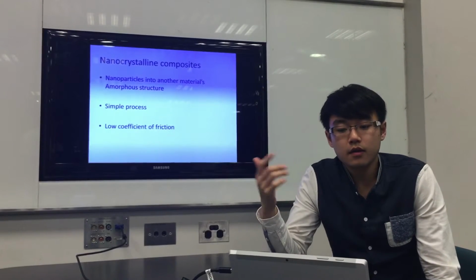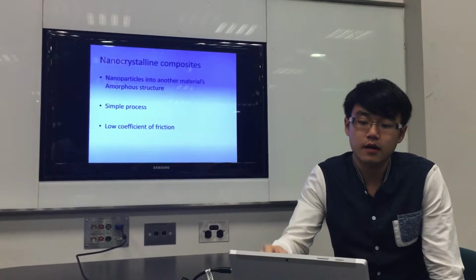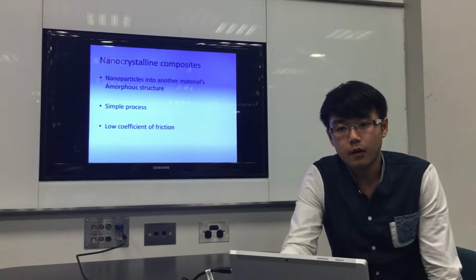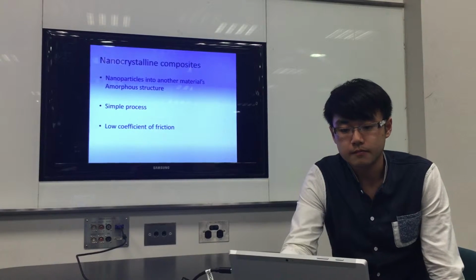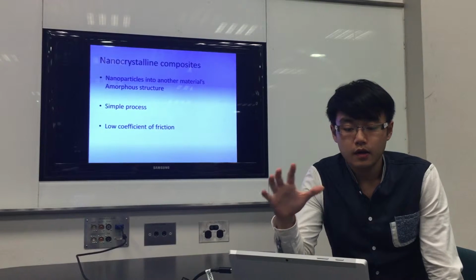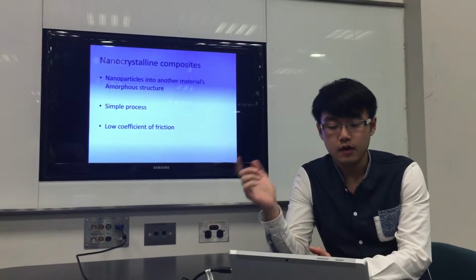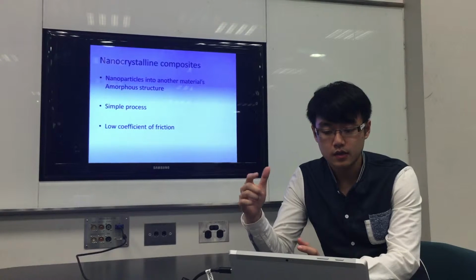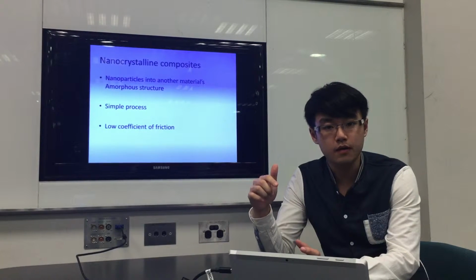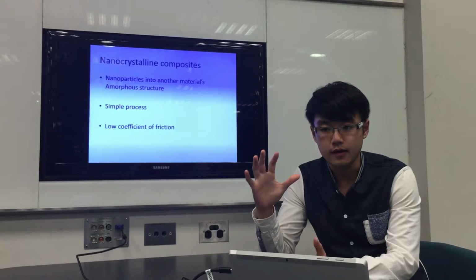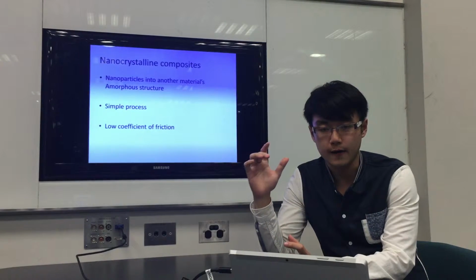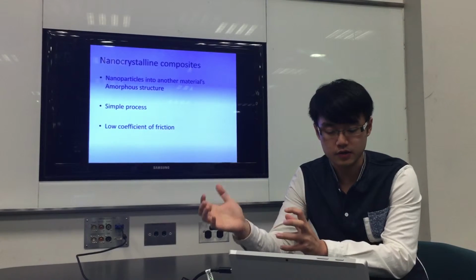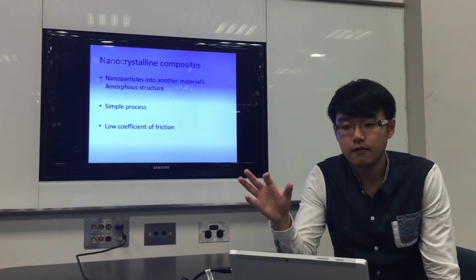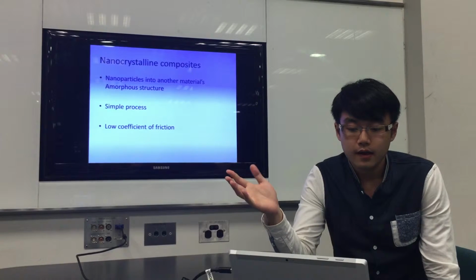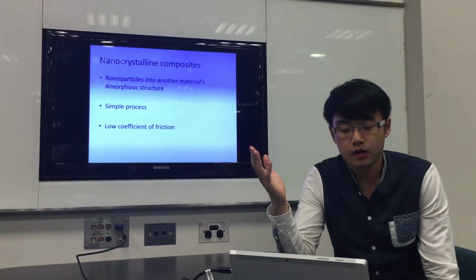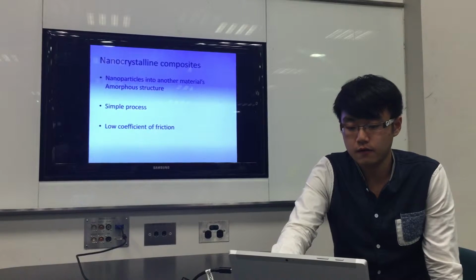So in the other part, the nanocrystalline composite will be a very general material coating. The nanoparticles will be in other materials. The other material has an amorphous structure, and we put the nanoparticles into this material, and they combine together. It will be a very stressed structure. And we can see it's a very simple process, and it has a very low coefficient of friction.